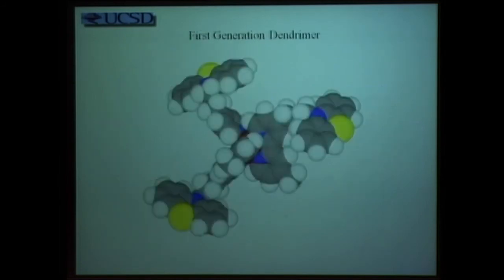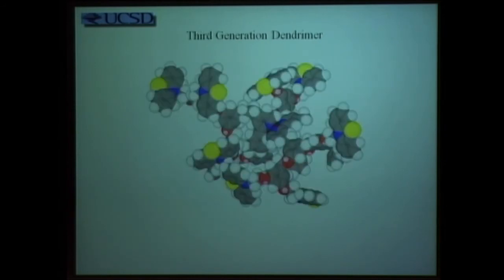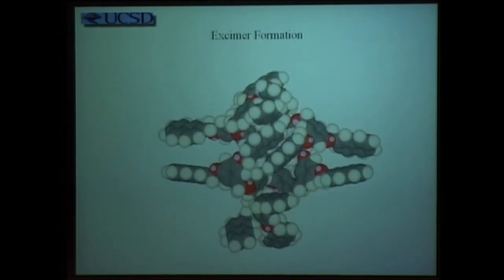Just to give you a picture from theoretical generation, here's what the first dendrimer looks like. You can see that the three units are displayed in such a way that they hardly interact at all. Here's the third generation dendrimer, and you can see that the approach along the blue line to the center of the reagent is blocked in several other directions. You can also see that if you look at the second generation, there are groups that are positioning themselves in such a way that they can self-quench. And as a result, the chemistry which is observed is very much less efficient. So this gives us design criterion by which we can go forward in understanding these systems.